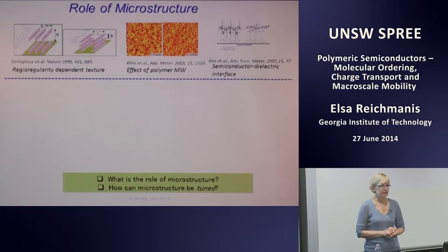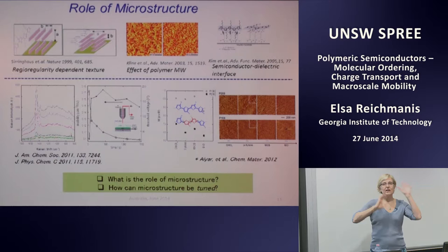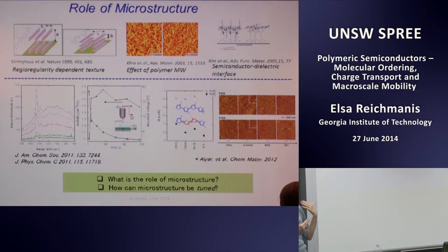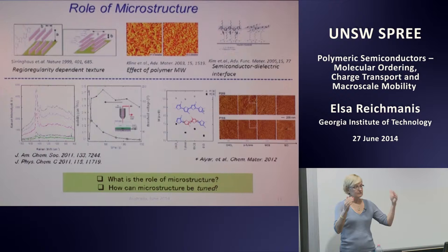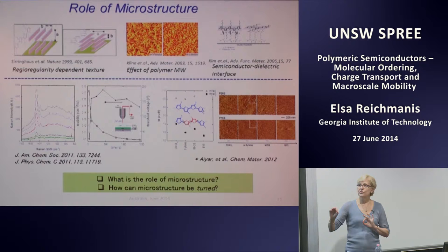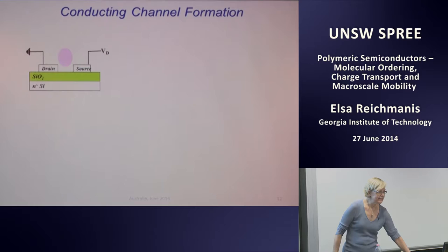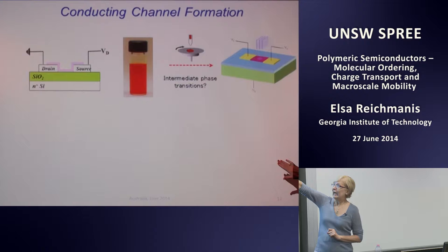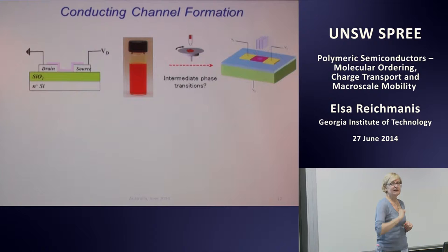All right, and what I'll start out with is talking about some of the work that we've been doing in our labs related to how we can manipulate the morphology of poly-3-hexylthiophene in solution in order to then control that microstructure. So looking at conducting channel formation, we're using spin coating for the most part. We dissolve poly-3-hexylthiophene in a solvent, we drop it onto a device substrate, we form a thin film of material, and then we make the device measurement.